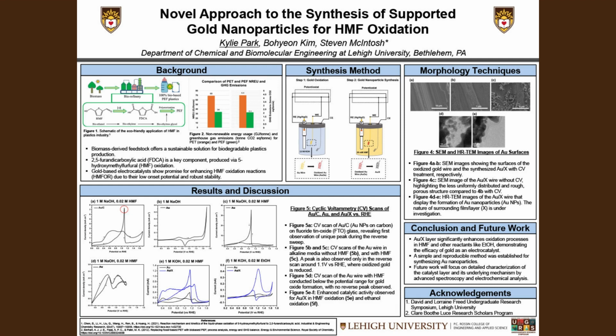By testing this AuX electrode in CV scans in potassium hydroxide with HMF, there is significant enhancement in electrocatalytic activity, as seen by the increased current density compared to regular gold wire in Figures 5e and f, for both HMF oxidation and ethanol oxidation respectively. This confirms our hypothesis that electrochemically treated gold, AuX, with its increased active surface area, enhances current density and serves as a superior catalyst for HMF oxidation.